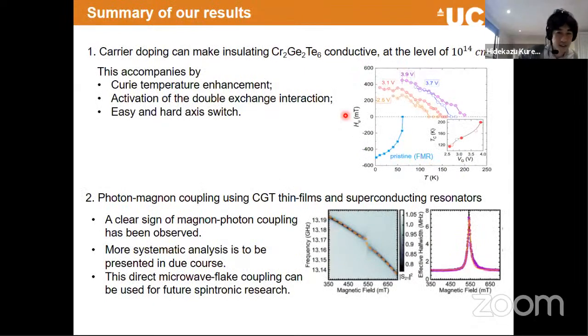So I think it's time to wrap up. I just want to show the main results of carrier doping, by both electric field and chemical doping. We can tell that the Curie temperature can be enhanced significantly by the mechanism of double exchange interaction. Accompanied by that, we observe this anisotropy switching, which is interesting to observe. The second part is a quick show of this magnon-photon coupling using the superconductive resonator and